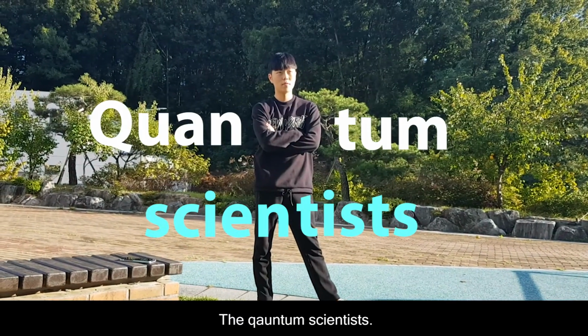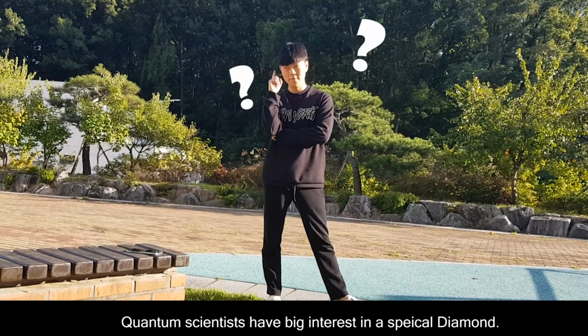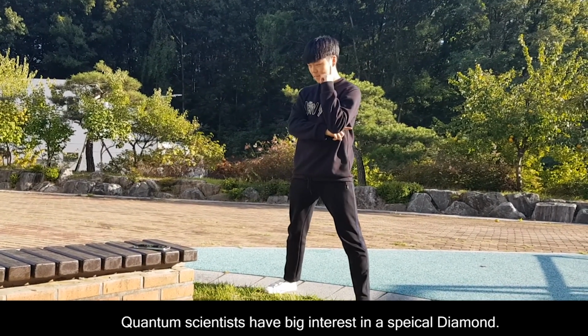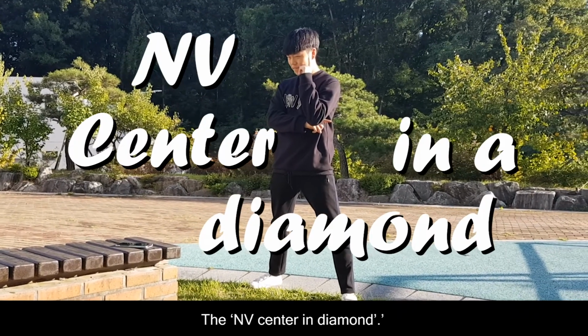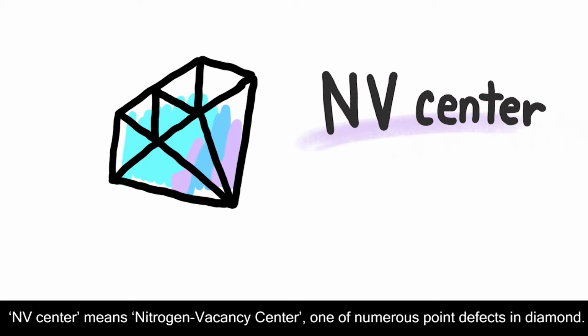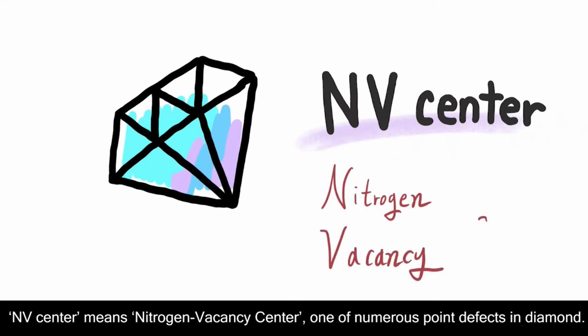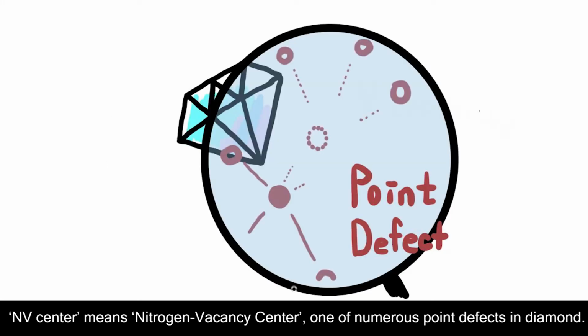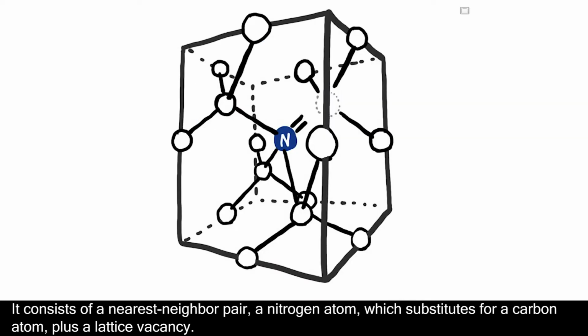But there are some people who are happier than anyone else to see such diamonds: the quantum scientists. Quantum scientists have a big interest in a special diamond, the NV center in diamond. NV center means Nitrogen Vacancy Center, one of the numerous point defects in diamond. It consists of a nearest neighbor pair, a nitrogen atom plus a lattice vacancy.